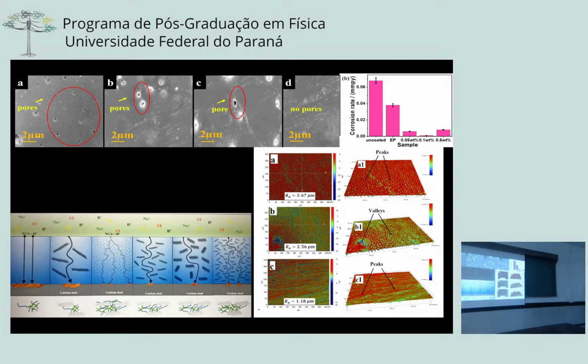Here what you see, this is metal with epoxy, which reduces corrosion, but if you add just 0.1 gram of green graphene, you get multifold enhancement, almost 3 orders of magnitude improvement in corrosion resistance. When we look back, what is the reason? I'm not going to go into full detail, just quickly for you to understand. These are scanning electron microscope images.